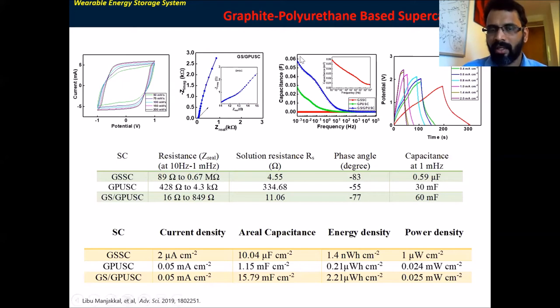As you can see here, in terms of capacitance, when GSSC only, it's not zero, it's a logarithmic scale. It's almost in the microfarad range. And then you can see here from the charging discharging analysis, with increasing the potential or the current density, it's almost going to 2.5 volt, but there is an IR drop here. After considering the IR drop, I used 2.2 volt.